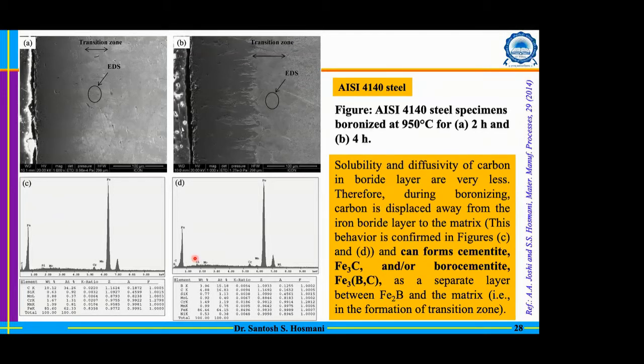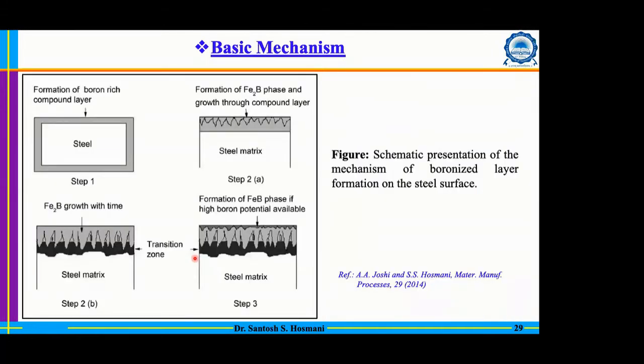And that is forming undesired compounds in the transition region. Because of that, that region has different properties than the matrix as well as the compound layer. In this case, we observed its enrichment with respect to carbon, and we also have an indication of boron there. That means there is a possibility of formation of cementite, or borocementite. Because of that, the properties are different compared to the matrix as well as the boronized layer. So now the basic mechanism is very clear to understand, and this is what I already explained.